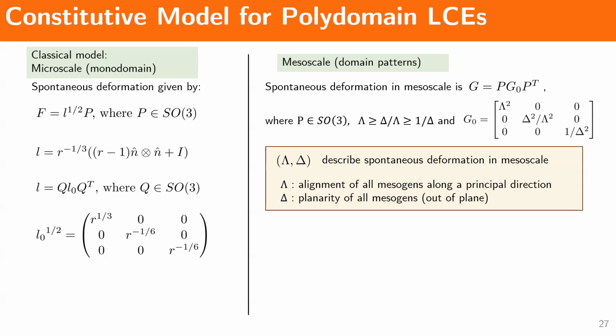In particular, lambda and delta describe roughly, in a coarse-grained manner, the spontaneous deformation in the mesoscale. You can derive from statistical argument and physically link lambda to the alignment of all the mesogens along the principal direction of the RVE, and delta to the alignment of all the mesogens along the out-of-plane direction of the RVE. I won't show that here because that's a little too much detail, but I'm happy to talk about it after.